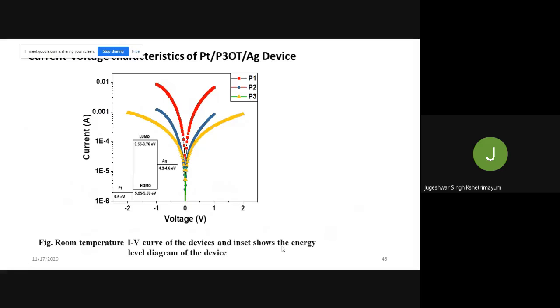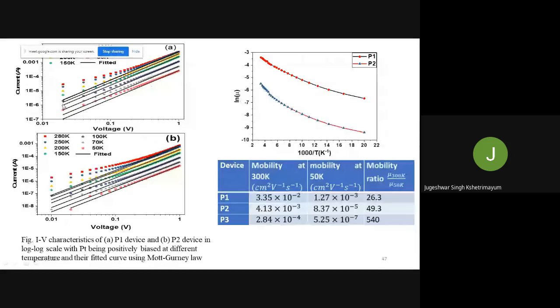Now we do the IV characteristic. Here the IV characteristic shows almost similar behavior because the work functions of silver and ITO glass are almost similar, unlike silver and stainless steel in the earlier methyl thiophene case. So we observe symmetric behavior. Then we do the same thing for the Mott-Gurney law: we apply it to the IV characteristic and find the mobility. This is for the P2 sample and this is the P1 sample. P1 has higher mobility, meaning a higher conductivity sample compared to P2, but the patterns are similar. Here I'm not able to show P3, but it is available here, and the ratio also shows a higher value for 540.